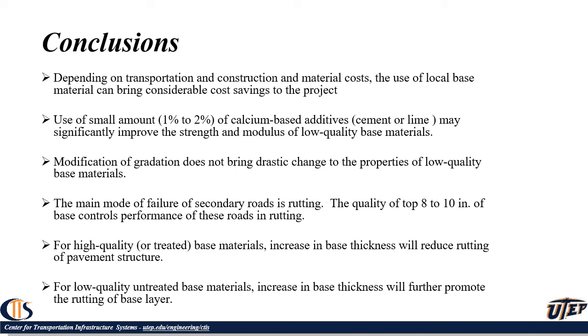The goal here is not to stabilize the material, but to improve it so that it will be comparable to a high-quality granular unbound base. Modification of gradation doesn't seem to bring drastic change to the properties of low-quality base material, but it can do some improvements to the other specification materials. The main mode of failure for the secondary roads is rutting, of course, and the quality of the top 8 to 10 inches of the base controls the performance of this rutting. So it's imperative to have high quality or improved material in the top 8 to 10 inches.